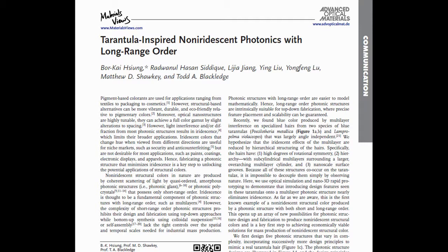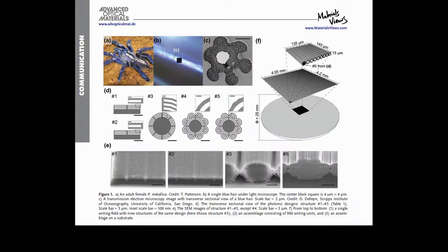They carried out transmission electron microscopy to find out the internal microscopic structure of the spider leg — the structures which give it this blue color. Then they made the structures using a Nanoscribe that uses two-photon polymerization with a writing resolution of 200 nanometers. Finally, through trial and error and theoretical simulation, they perfected the design which actually mimics the blue spider.